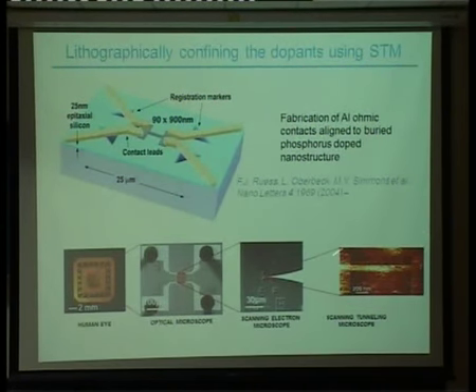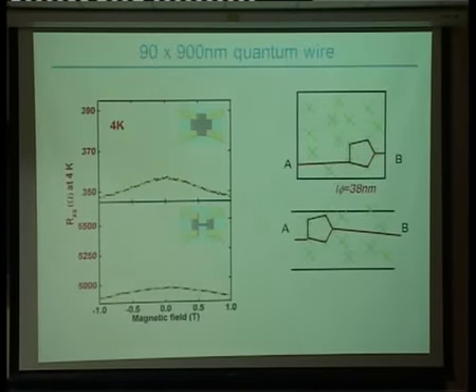And so one of the first devices that we tried to make was just a simple quantum wire structure. We designed this device really to show us how the conduction in the device worked, to show us this kind of phase coherent effect. So if we look at the conduction, we pattern 2 devices at the same time. We're looking at their magnetoresistance here. This is our 90 nanometer wide wire by 900 nanometers long and a 4 by 4 micron square. And as I said before, these crosses represent the phosphorus atoms where the electrons are traveling through. You can see as the electrons come through, they scatter off the phosphorus atoms and they form these phase coherent loops. And you can see the signature of this weak localization in the magnetic field data at 4 Kelvin.